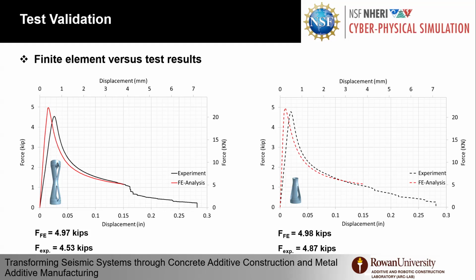And our goal now is to go back and understand the strain and stresses and correlate that to the numerical model. Yeah, we tried to do mechanical testing to quantify the material properties. Yes, this is a plan, but for the model we use the fabricator's stress-strain curve. The fabricator has a set of stress-strain curves for dog bones using this technique, but our shape is not straight like a dog bone. It has a lot of contribution, and we also do bead blasting to remove the dark heated outside. We asked them how much they removed, and we tried to incorporate that in the model after, but this was prior to testing, so it's a predicted analysis.